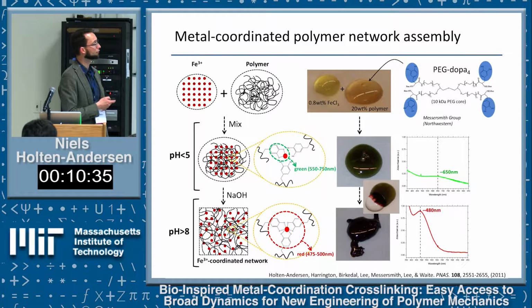What you get when you mix these two together is initially a low pH solution, because the iron ions drop the pH of the solution. Low pH gives you weak binding between the organic ligand and the metal ion. Because metal coordination chemistry has been so well studied in the literature, it's well known that you can look at the color changes from the interaction between ligands and metal ions to understand what type of interaction you have. When these two fluids mix, you get a green fluid, and that green color is known to come directly from the absorption of this complex.